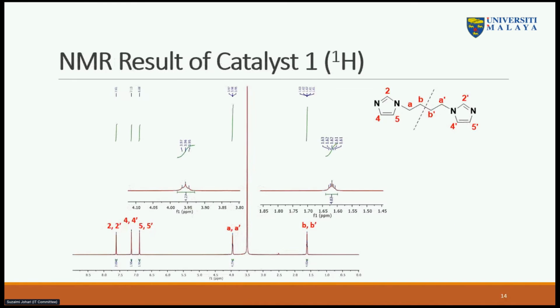And also, okay, so this is the result for the NMR, which has shown the high purity of the compound produced. As we can see here, this is attributed to the hydrogen in the imidazole, and these two peaks are attributed to the H from these two carbons here on the aliphatic side.